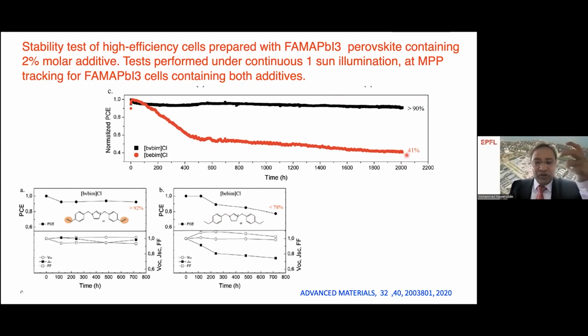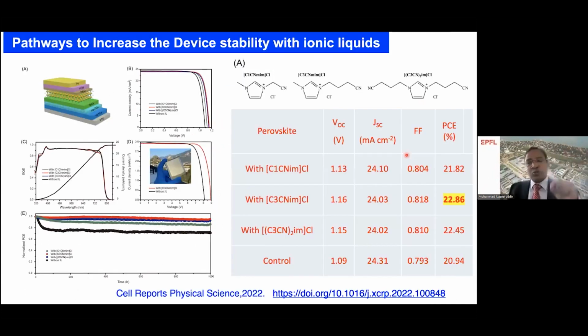So that's the beauty of modification of these materials, either by fluorinated cations or self-polymerizable ionic liquids. I have one more example to show, another very interesting piece of information. When you are forming these perovskite thin films, usually they form by an uncontrolled crystallization process. Can we control the crystallization process by bringing in an ionic liquid that has a second functionality? What is that second functionality? You have a cyanide. Cyanide is a coordinating group. So it coordinates to the lead 2+ and slows down the crystal growth, and therefore you can control the morphology